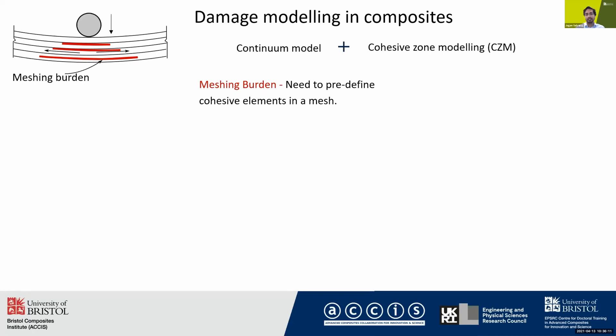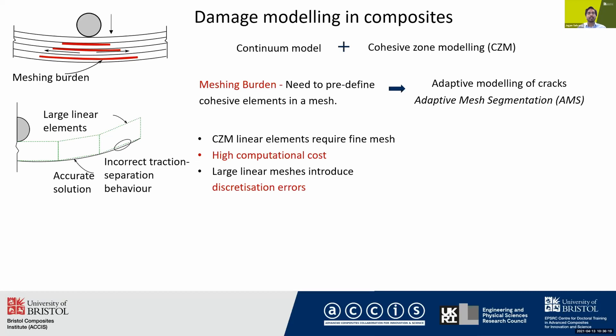To address this issue, an adaptive modeling method is developed in this work. Also, the standard linear elements require a fine mesh discretization, which increases computational cost. To solve this large meshes problem, a higher-order cohesive element formulation that introduces C1 continuity is developed.